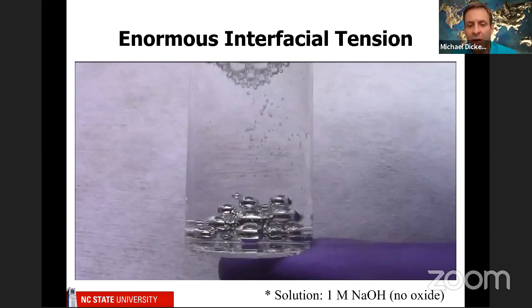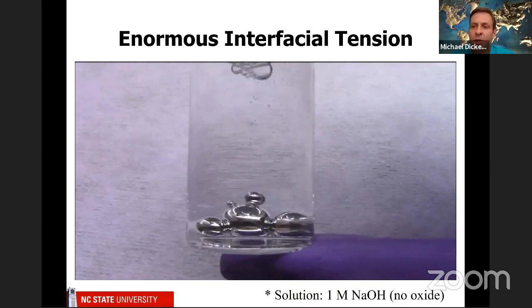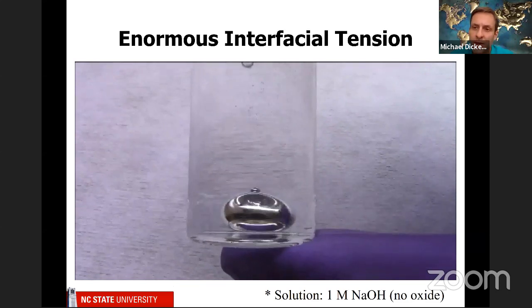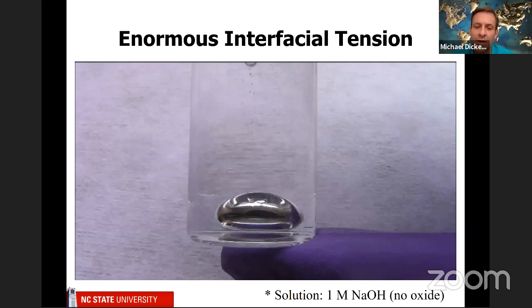So this is a vial of liquid metal sitting in sodium hydroxide. Remember, sodium hydroxide keeps the metal free of oxide. So when you shake it, you can break it into droplets, but it very quickly beads back up and forms a sphere because, of course, a sphere minimizes the surface area and therefore the surface energy. One thing about this liquid is it's got the largest surface tension of any liquid known at room temperature. And it's not even close. It's 7 or 8 times bigger than water.